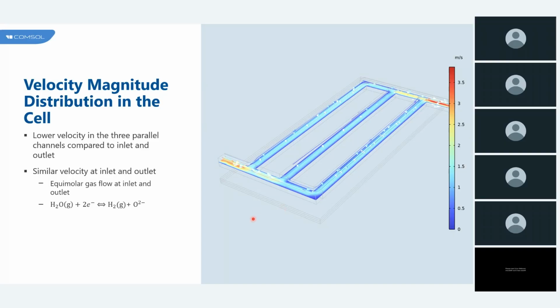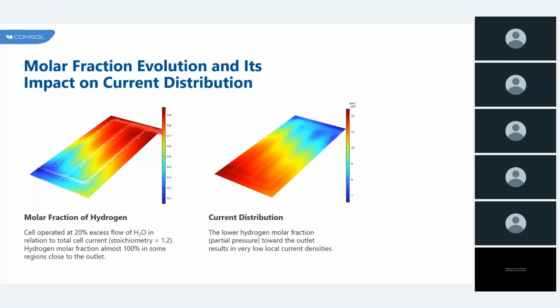So these insights are critical for optimizing gas feed ratios, which prevents the performance losses and ensures high efficiency under realistic operating conditions. So now let's examine how changes in the gas composition, particularly hydrogen concentration, can directly affect the reaction rates and overall cell performance also. So here the simulation results show that higher hydrogen molar fraction near the outlet leads to a drop in hydrogen partial pressure, causing a decline in the local current density.